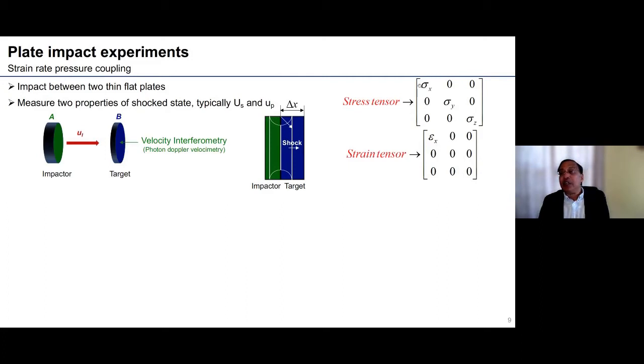And here you have the normal stress and the transverse stresses. Due to the inertial confinement, at very high pressures, you could approach a hydrodynamic state of stress. Nevertheless, the strength of the material is important at these high pressures. That means the transverse stresses, sigma y and sigma z, which are equal, differ from the normal stress, and that's where you have the shear stress.